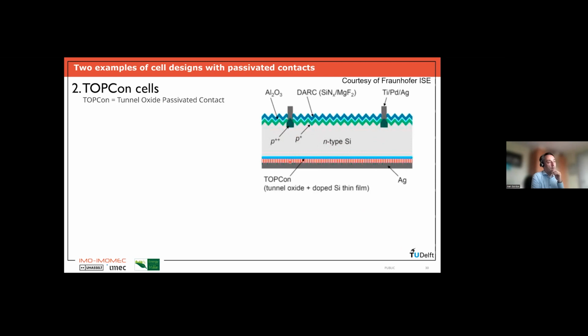So typically at the rear, the rear of the silicon is passivated with a thin oxide layer. We call it a tunnel oxide because the current has to tunnel through it. And then on top of that oxide, we have a doped silicon thin film, typically a doped polysilicon film that actually gives you a surface field.